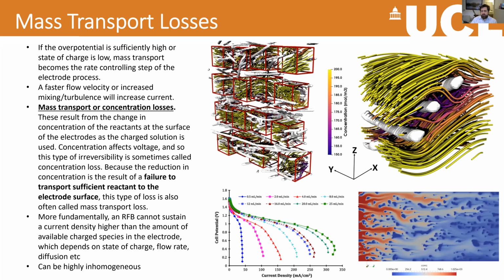The final consideration for these losses or overpotentials is mass transport losses, and these are really important in flow batteries. They're important in fuel cells as well, and also in lithium-ion batteries. Essentially, this comes about from the fact that if we try and demand a high current density from our battery, this means that we are, because of Faraday's law, requiring a high rate of reaction. And that rate of reaction can only be satisfied if we can bring enough reactants to the surface of our electrode where these reactions happen, and to have a high enough concentration of reactant species to satisfy that Faradaic link between the current density and the rate of reaction.